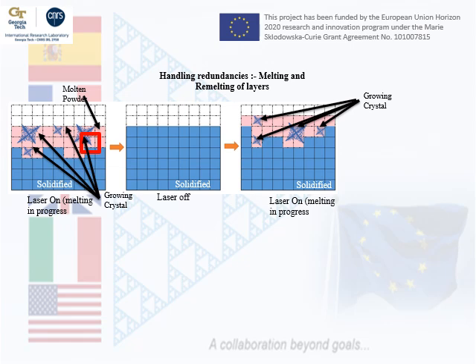Now, before we continue, we also have to discuss something that is very particular to additive manufacturing, and this is the case of remelting. Remelting happens in additive manufacturing because the laser can pass a position several times, since there is melting of powder layer by layer. So it is possible that one cell experiences more than once a temperature higher than the melting point, and this event is called a remelting event. The problem in simulations with remelting is that when this happens, we have to reallocate and shuffle memory. Regarding the computational implementation of the model, these two events are very inefficient, and this essentially means that it is going to slow down the simulation.